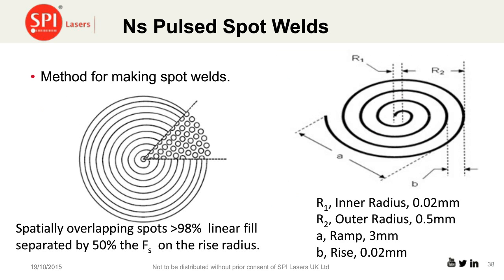When we talk about a spot weld, it's very different to some of the other spot welds that you may have experienced. What we do is create these by spirals, like little scales, where we can spiral outwards or inwards and create a nugget that creates a spot. And this is made up of millions of pulses. It creates a very good joint with the material.